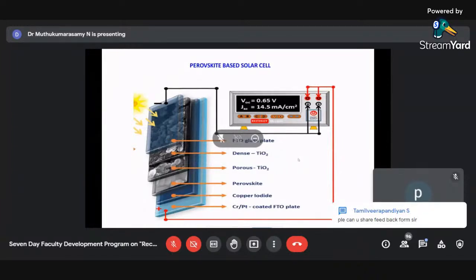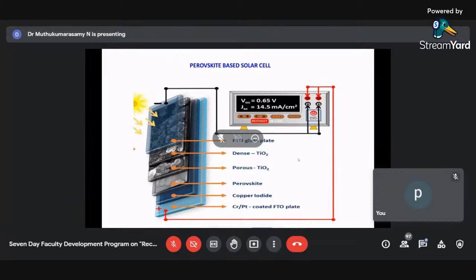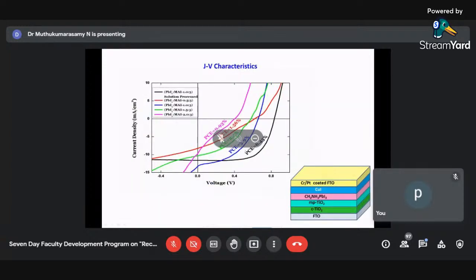And this is the perovskite solar cell which we fabricated. You can see we got a JSC of 14.5 milliampere, and the open circuit voltage is low, 0.65 is low for a perovskite solar cell. We have to get nearly 1 volt. And this was the structure which we fabricated. We had the chromium, copper iodide, perovskite, dense TiO2, then mesoporous TiO2. And we got an efficiency of nearly 3.9% for the powder press technique.